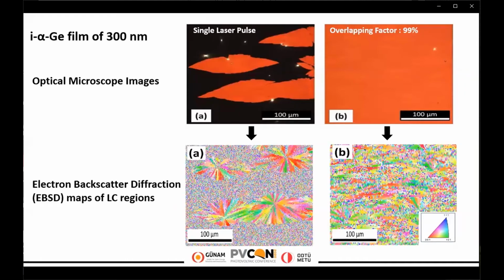Defect formation and damage of the film can be avoided with an optimized laser fluence of 110 millijoule per centimeter square. And we used overlapping factor to get large crystallized area. Microstructures start from a random nucleus with a single pulse and extend radially outwards, generating fan-like microcrystal domains with different orientation.